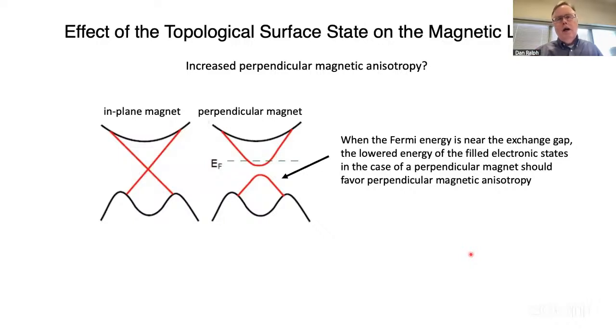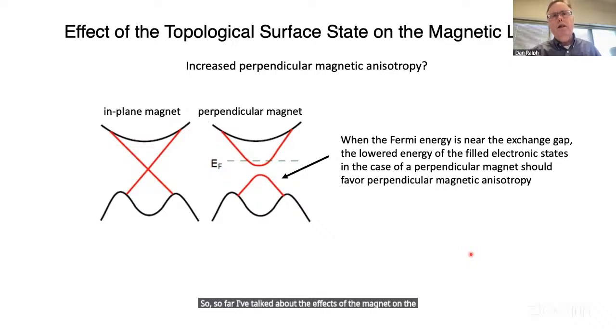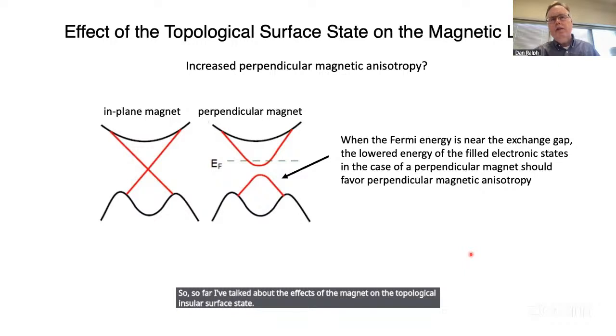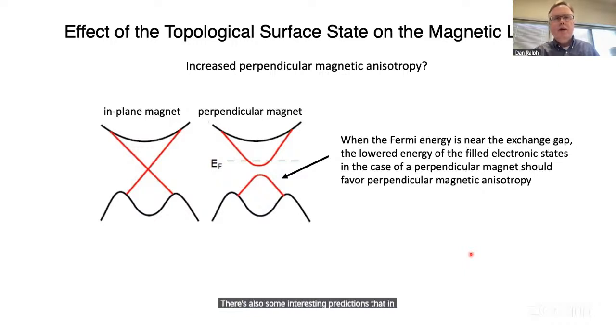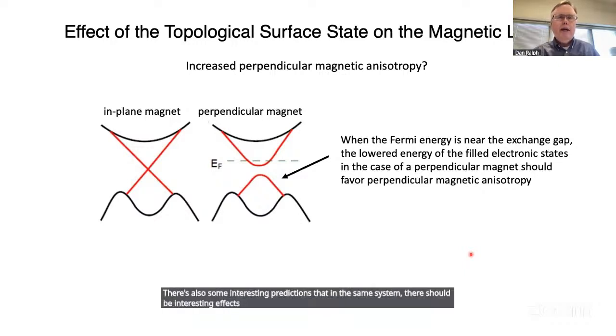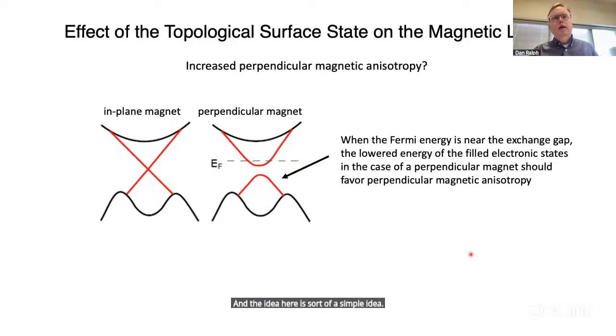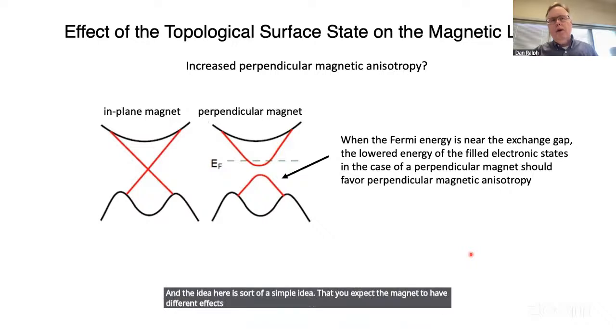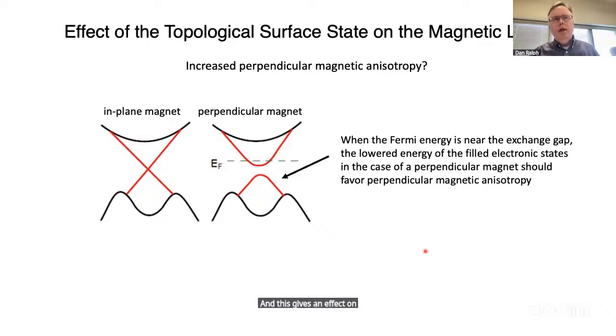So far I've talked about the effects of the magnet on the topological insulator surface state. There's also some interesting predictions that in the same system, there should be interesting effects on the magnet given by the topological state, so the other way. The idea here is sort of a simple idea that you expect the magnet to have different effects on the surface state depending on whether the magnet points in plane or out of plane. And this gives an effect on the magnetic anisotropy.